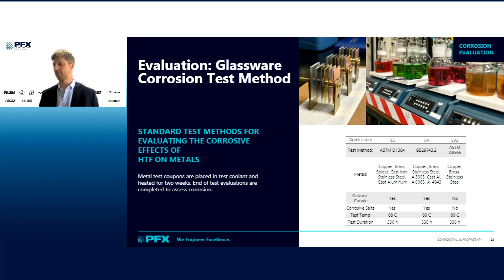And then at the end of the test, we tear it down. We clean this metal specimen. They go through a water wash and then an acid wash, and we take a weight of them. And we can measure a weight loss from before and after the test. And that tells us what our rate of corrosion is for that specific metal in this bundle with a specific coolant.